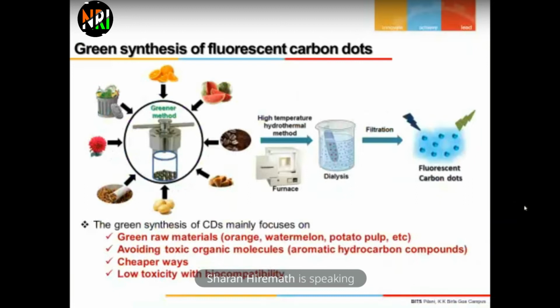Here we can see from the thermal method, hydrothermal method, we can use orange, watermelon, potato pulp. We can also use waste food as the green source or the carbon source for the preparation of carbon dots, and they are prepared at different temperatures according to the size, according to the properties, according to the excitation as well as the emission wavelength of the carbon dots. We can vary the temperature in the hydrothermal method. Then we can go for dialysis for the filtration, and we'll get the fluorescent carbon dots. So these carbon dots can be prepared from green materials, and they avoid organic molecules, and these two will ensure the synthetic method is very cheap and it has low toxicity.